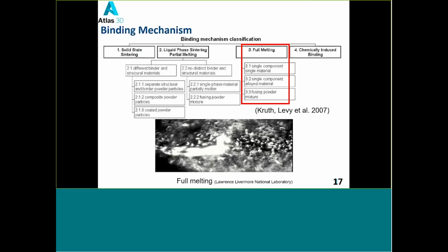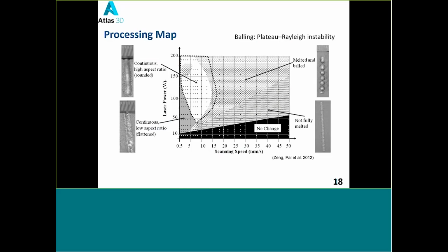So, for example, there are quite different types of binding mechanism used by metal AM, and the most popular one is the full melting. In the full melting, we can build a full density part. That's why people like it. However, in the real build process, when we have different laser power and different scanning speed, we will get different profile of the part. For example, if your scanning speed is too fast or the laser power is too low, you will get partial melting. And if you have a very high laser power or very low scanning speed, you will have this balling effect. In order to achieve this continuous high aspect ratio profile, you really want to have a good combination of the laser power and scanning speed.